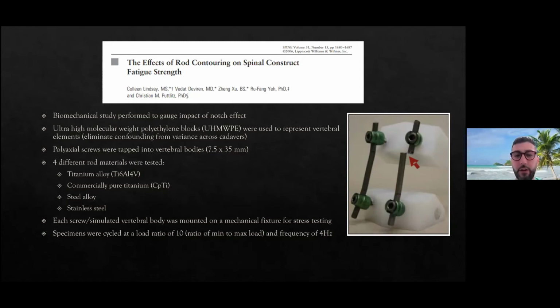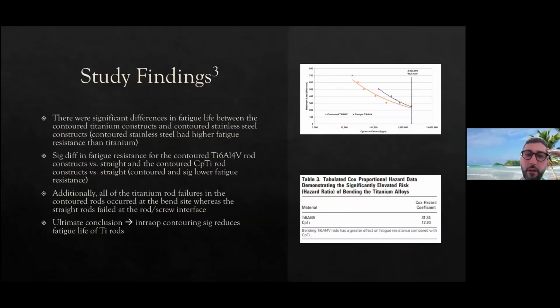That just means that's a ratio of min to max load. I didn't put up exactly what the loads were here. It's not really important to understand the results. But what did they find? Basically, they found significant differences in fatigue life between the contoured titanium and contoured stainless steel constructs, with stainless steel having a higher fatigue resistance, and significant difference for the contoured titanium rod versus straight rod, and contoured commercially pure titanium rod versus straight. In other words, the contouring of the rods significantly decreased the fatigue resistance.